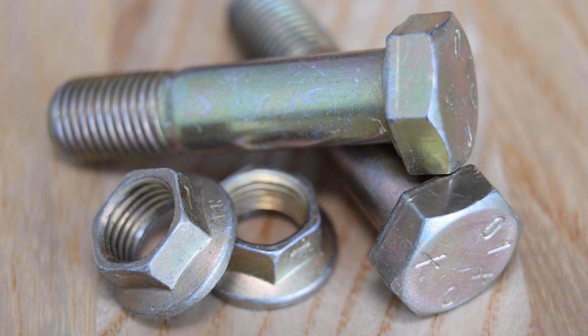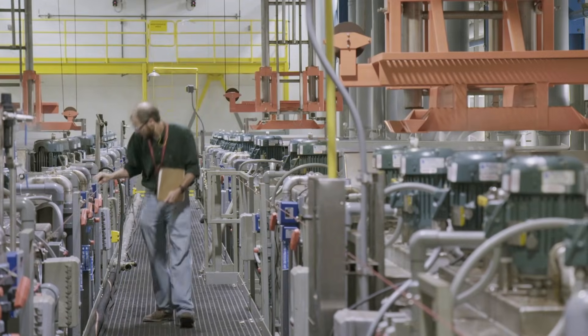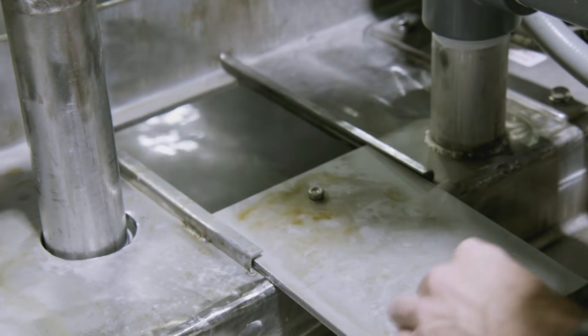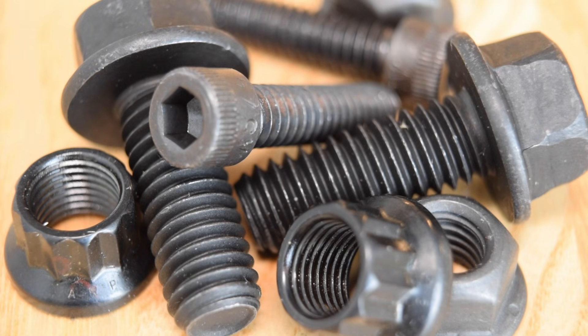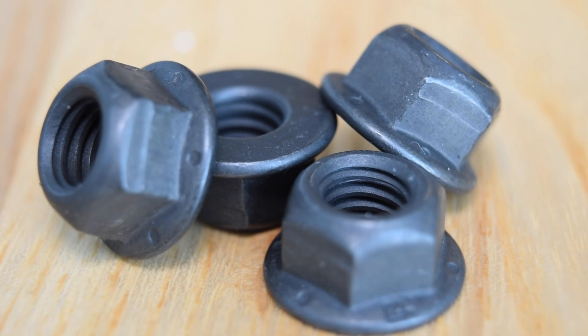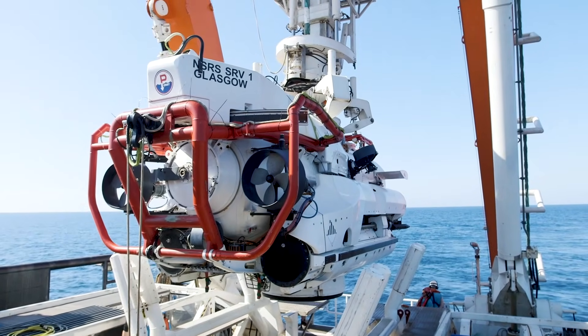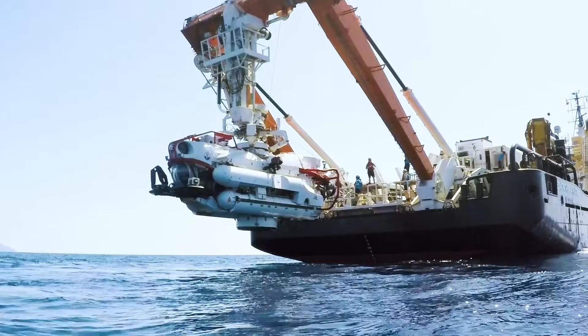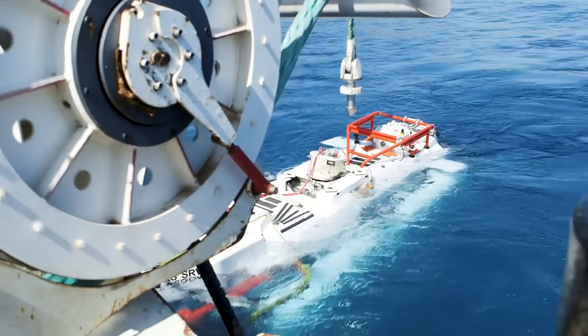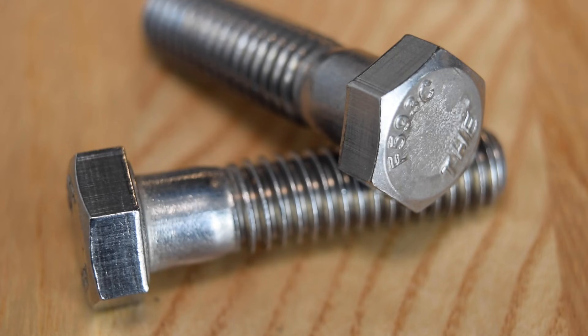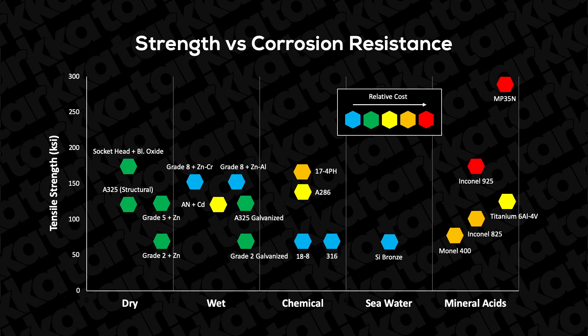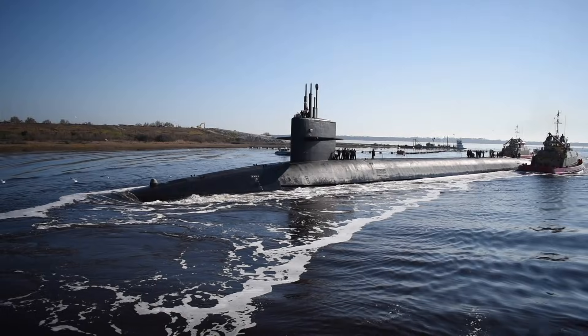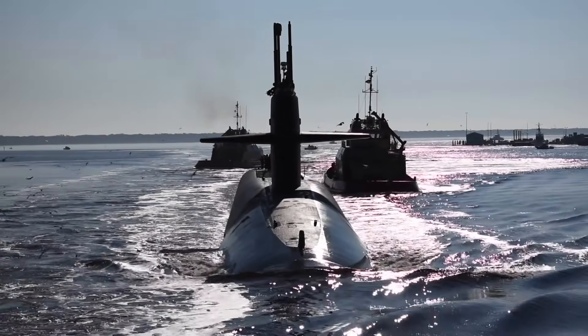Aerospace fasteners are usually plated with cadmium. This is a very effective coating, but cadmium is an extraordinarily dangerous material and these hazards are compelling manufacturers to find safer alternatives. Some fasteners, particularly socket head cap screws, are coated with black oxide, and while it looks nice, this doesn't significantly improve corrosion resistance over bare steel. Coatings are generally not sufficient for applications in which the fastener will be immersed for extended periods. Switching to a stainless steel fastener made from an alloy like 304 or 316 improves corrosion resistance, but 300 series stainless is not nearly as strong as alloy steel. If you need both high strength and corrosion resistance, you may need to use a super alloy like A286 or 17-4PH.